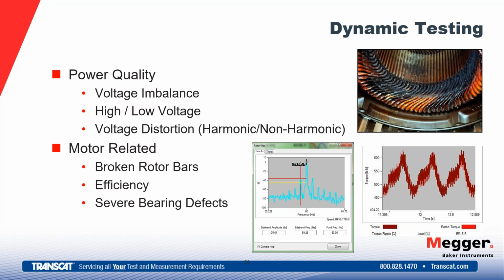Dynamic testing is going to help us, again, assess the environment of the motor, where it lives. We're going to assess that power quality, voltage imbalance, high or low voltage. So again, we'll set parameter thresholds, usually set at 10% for high and 5% under for low-end voltage, and voltage distortion. Especially voltage imbalance and voltage distortion are causing currents that are circulating in the opposite direction from what we need them to. So it's working against that motor.